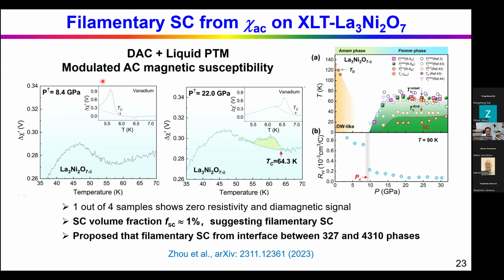They use this modulated AC susceptibility technique. So basically, this technique is more sensitive than the conventional mutual induction method. So they use a reference vanadium, which is also a superconductor under pressure. By comparing the signal of this transition, they can estimate the superconducting volume fraction of the nickelate superconductors. So they found that the superconducting volume fraction is on the order of 1%. So it's quite a small superconducting volume fraction.